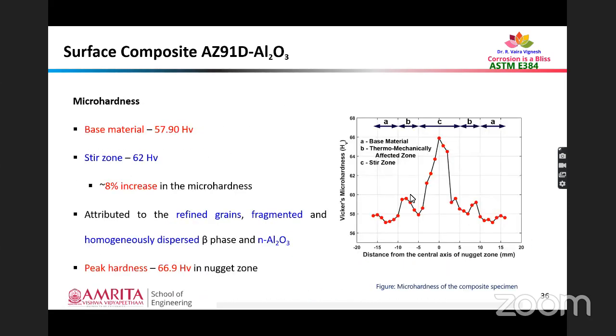And coming towards microhardness, the base material's microhardness was around 57.9 HV, taken at a load of 100 gram force, and the stir zone had 62 HV. So there is approximately an 8% increase in the microhardness of the material. This hardness improvement is attributed to the presence of refined grains, and fragmented and homogeneously dispersed beta phase and nanophase alumina. Coming towards the peak hardness found in the material, that is the surface composite, it was around 66.9 HV in the nugget zone.